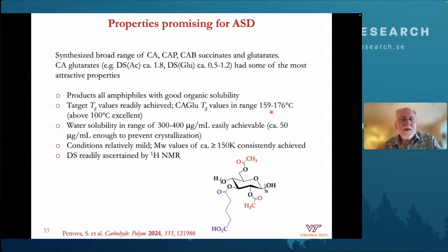And the properties of those polymers were pretty encouraging, right? They're all amphiphiles. We said we needed amphiphiles. They're all very high TG polymers, up in the 160 to 175 degree range, way over the 100 centigrade target that we have for these polymers. In spite of being amphiphilic, they're quite water soluble in the range of 300 to 400 microgram per milliliter, which is on the range of 6 to 8 times what we think we have to prevent crystallization and release the drug. Conditions to make them are relatively mild, so we're getting high molecular weight polymers, and they're pretty simple molecules. It's very easy to determine degree of substitution and even position of substitution by proton NMR spectroscopy.